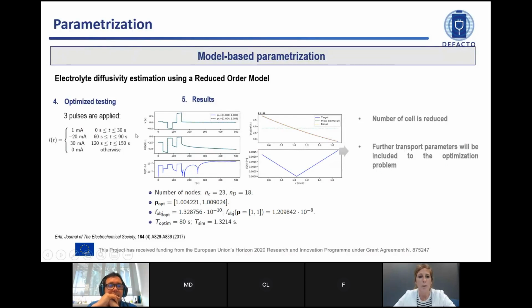Therefore, what we do is identify the best testing condition so that for one test or one cell, we can identify properly the parameter. So in the end, we did it in an iterative way. We made some trials with different testing protocols, and then we came out with this specific test. Running this test, we came with exactly the same pattern, so we can now say that we are able to identify properly this parameter by using only one test for a specific cell.